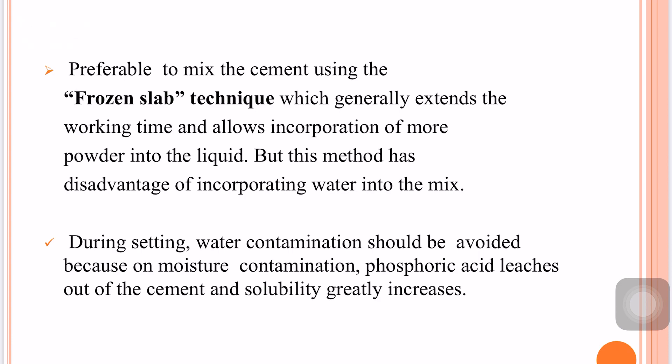Preferably, the cement should be mixed using a frozen slab technique, which extends working time and allows incorporation of more powder into the liquid. However, a disadvantage of this method is incorporation of water into the mix, which alters cement properties. During setting, water contamination should be avoided, as moisture causes phosphoric acid to leach out of the cement, increasing its solubility.